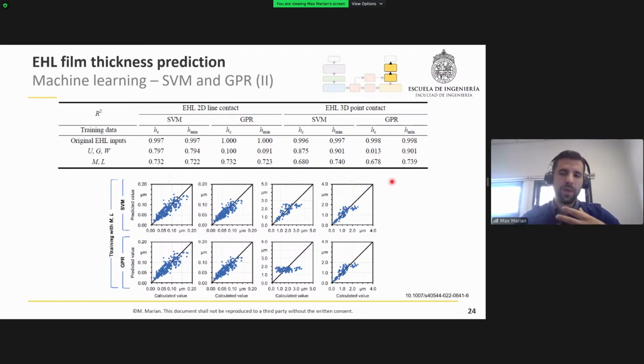And this inferior prediction accuracy, in our belief, can be traced back to redundant input variables for the different output variables, because we can have similar dimensional parameters that can result from different original input data, and with similar dimensional parameters we can obtain different predicted film thickness, for example, different minimum or central film thickness. And we believe that these inconsistencies in the database led to problems in the training of the SVM and the GPR.